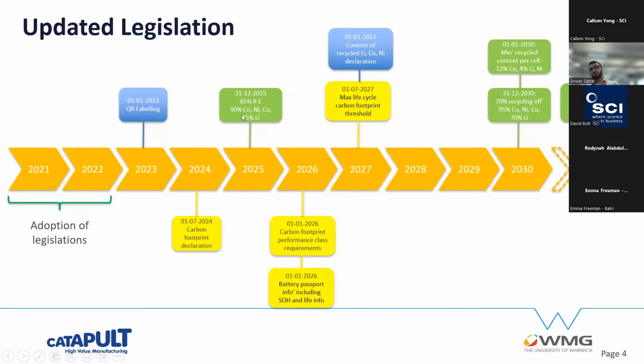And there's also going to be an introduction of recycling targets for certain metals. So 90% for the cobalt, the nickel, and the copper, and 45% for the lithium. And then in 2030, that recycling target is going to increase to 70%, and 95% recycling targets for the cobalt, nickel, and copper, and 70% for the lithium.